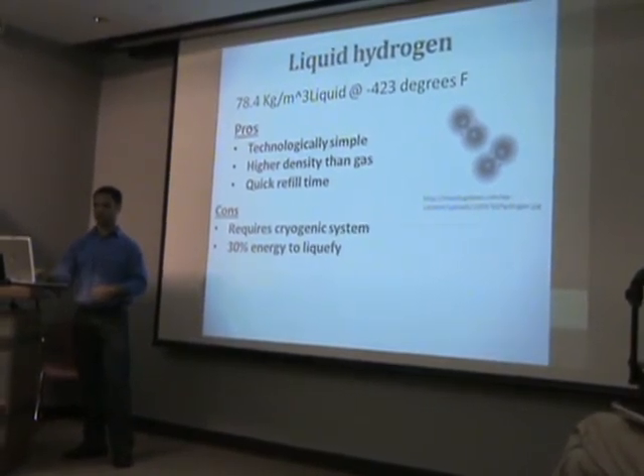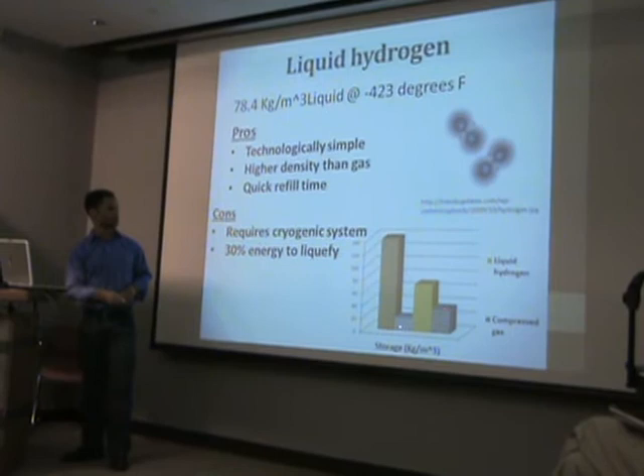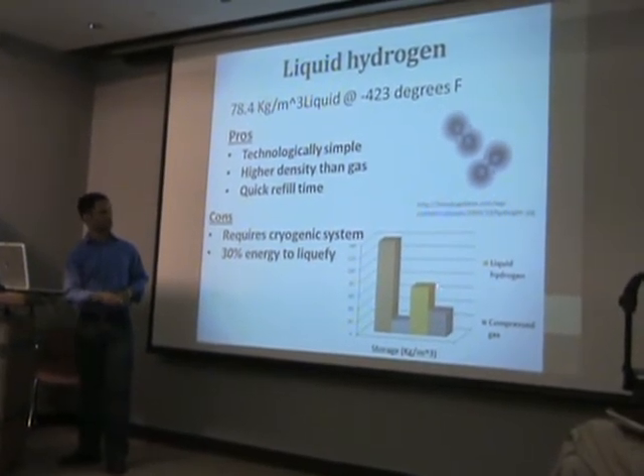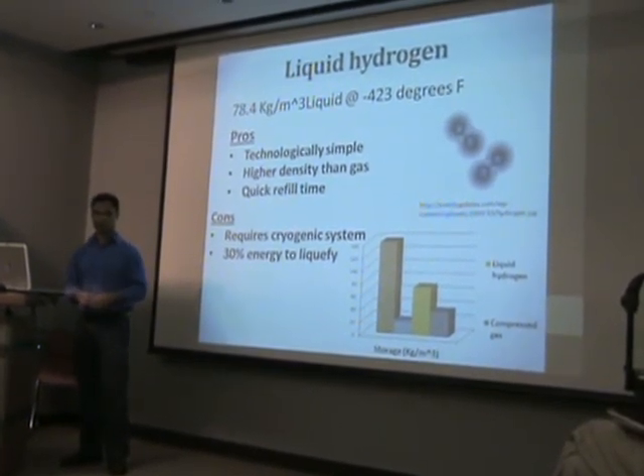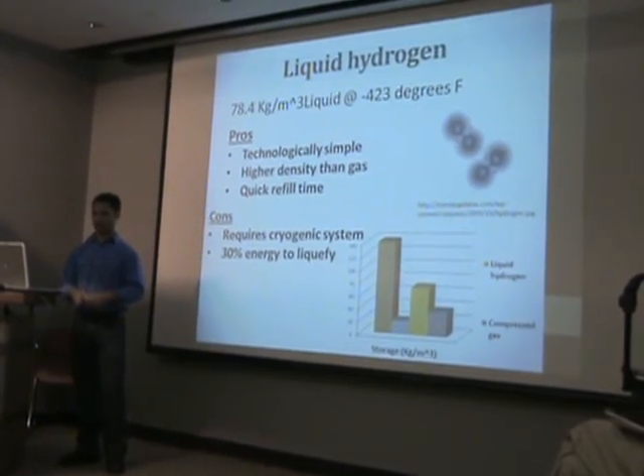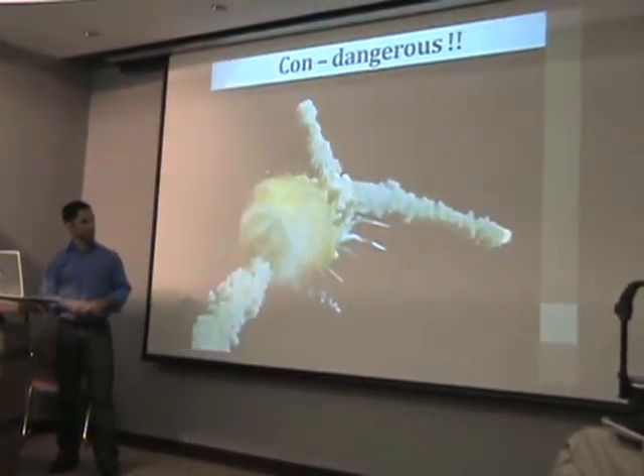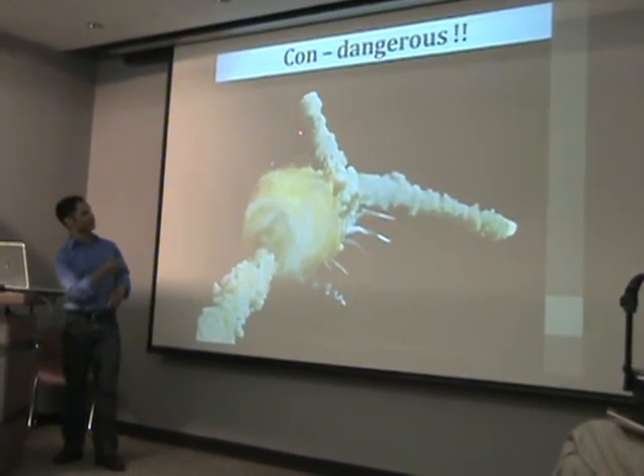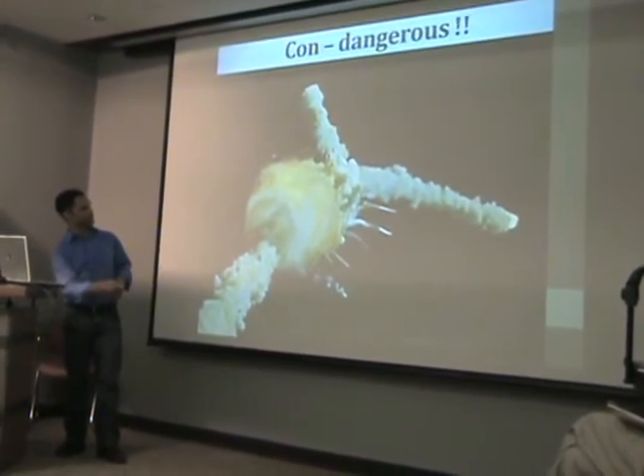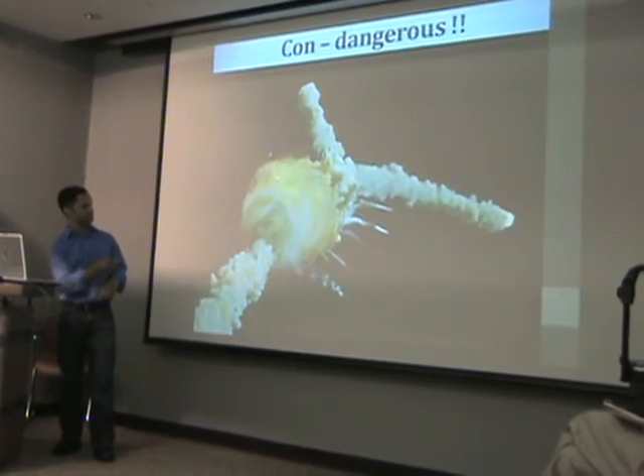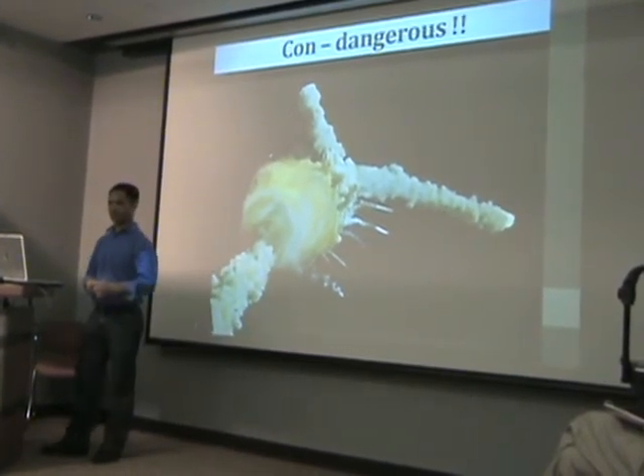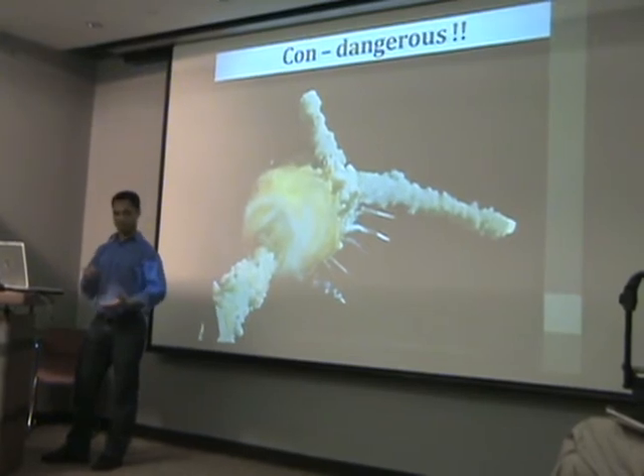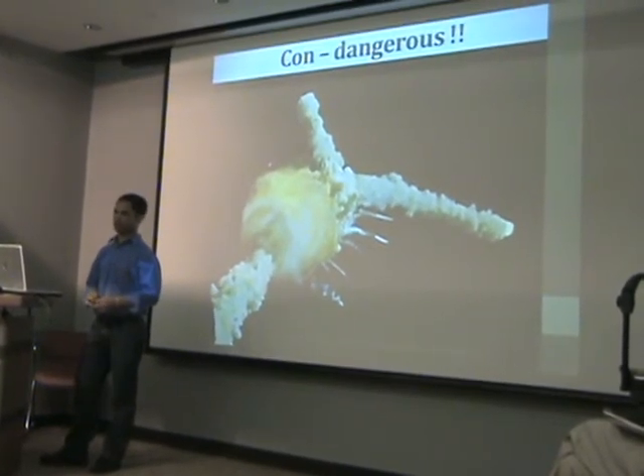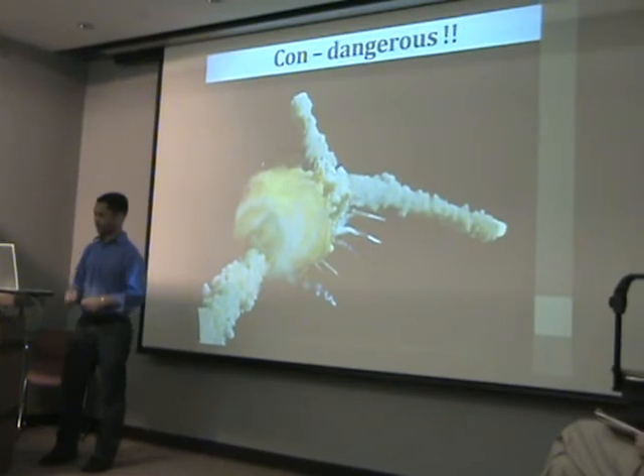So if we throw liquid hydrogen onto the chart, you see it's this one right here, which is better than compressed gas, but certainly is not the best option. And one other con for liquefied hydrogen, again, that's right, it's the safety issue. Here we have the Challenger disaster, and you can see the solid rocket boosters here, which actually one of them had a flame which caused the hydrogen tank to explode. And this is an issue for cars too, because hydrogen liquid constantly is producing hydrogen gas, which has to be taken care of. So you don't want this as a storage medium for your car.